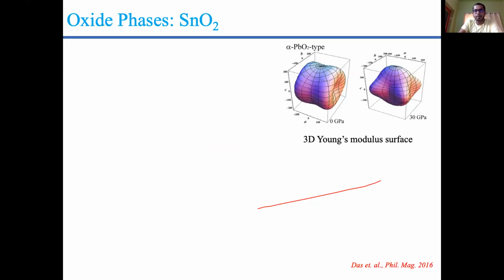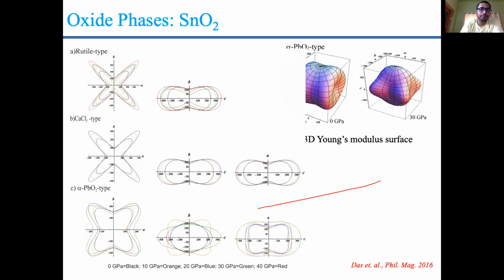I found that the Young modulus surface is totally distorted, but we can think of plotting the directional projections on different planes. So here are the projections. You can see for rutile and CaCl2 type, the ratio of Young modulus along the diagonal and in the axial direction on the AB and BC plane increases with pressure, which suggests the elastic stiffness becomes more anisotropic at higher pressure. Whereas the alpha PbO2 phase shows contrasting behavior of the directional Young modulus.